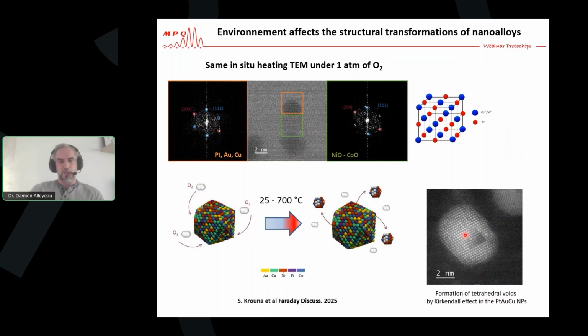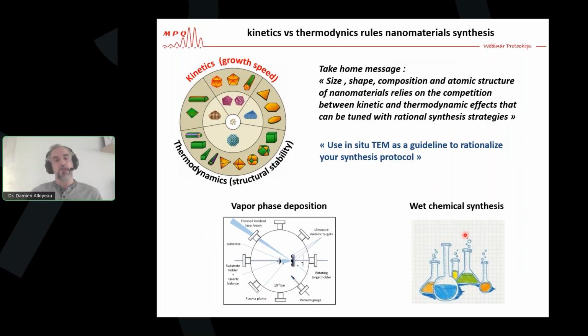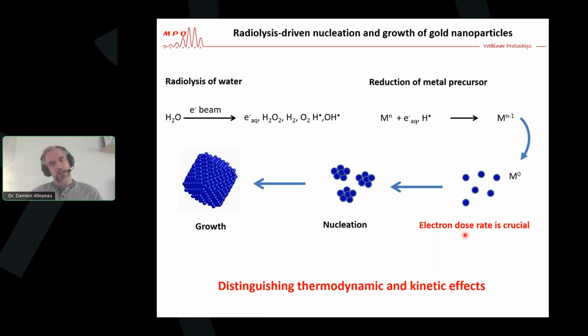So in the second part of this talk, I'd like to show you that my take-home message also applies to wet chemical synthesis. And of course, in that case, you will be using liquid phase TEM. So usually one of the main advantages when you want to study the synthesis of materials with liquid phase TEM is that we can use the radiolysis of the solvent as a driving force. When your electron beam interacts with a liquid sample, the electron beam can radiolyze your solvent. And in the case of water that I show here, you create a lot of radicals and molecular species, and some of them, such as these aqueous electrons or the hydrogen radicals, can reduce the metallic precursor that you have in the solution to the metallic state to induce the nucleation and the growth.